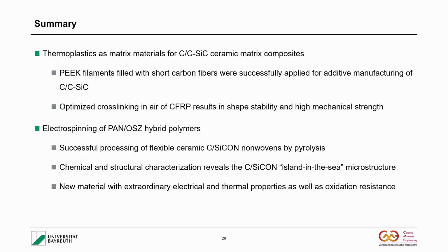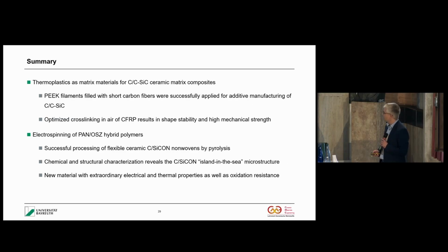So I would like to sum up my talk. First of all, we investigate a lot of thermoplastics as a matrix material for ceramic matrix composites. So you can use, for example, PEEK filaments for additive manufacturing. We did this for short carbon fibers in the last years. We also have to optimize the cross-linking in air of these CFRPs, so CFRP technology is very important for us. And then we investigate the electrospinning of these hybrid polymers, leading to these very interesting nonwovens with a very interesting microstructure, and they have this very interesting property that they have a low thermal conductivity, but a high electrical conductivity, as well as a high oxidation resistance.